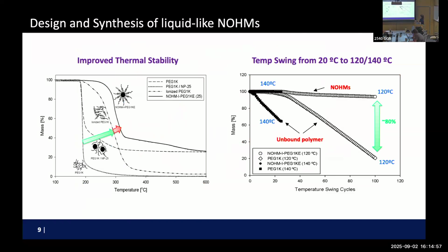Here, this is a great degradation of untethered polymer. As you tether them, it gets much more robust. I'm not going to be able to talk about why this is as robust, especially under oxidative conditions. This is very robust. In fact, this lasts 100 cycles, and I was a nice professor to stop the reaction then. My students would stop at 100 cycles. Compared to untethered polymer, it degraded almost to nothing.